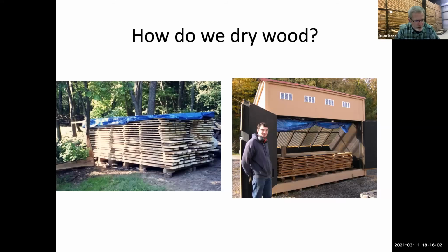Now, if I live in Durango, Colorado, or Las Vegas, Nevada, the humidity is so low out there, wow, sometimes it's less than 20%. So that's right around a 5% moisture content in wood. Yeah, I could get it all the way down there just by air drying it if I was willing to wait long enough. But most places in North America, I've got to put some heat to it. I've got to get the relative humidity lower in my chamber to get that wood to 6 to 8% moisture content. So that's why we use a dry kiln usually.